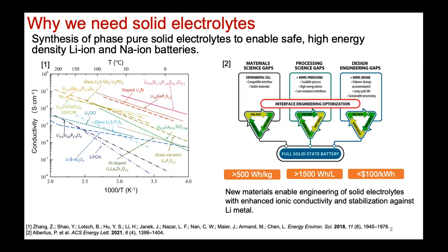But as you can tell here, when there's a change in your curve, that's a phase transformation with a different, at least a different mechanism of ion conduction. So that's something you have to worry about. And also, some of these compounds, so this is LGPS, as we call it, lithium germanium thiophosphate. It's one of the highest ion conductivity at room temperature as well. So you can see it's pretty high up on this curve, on the y-axis here. So things that are lower have lower ionic conductivity.